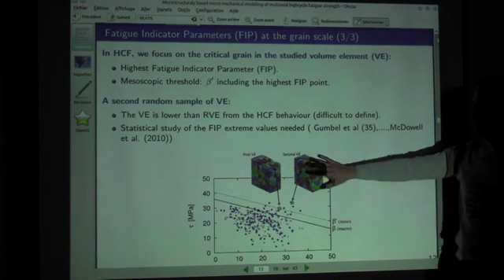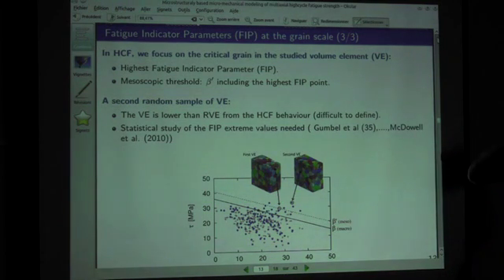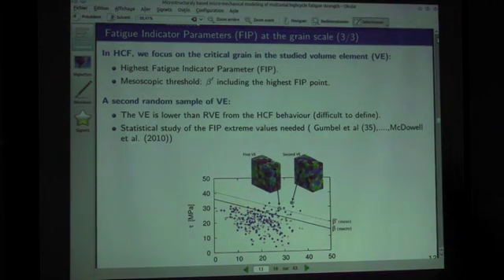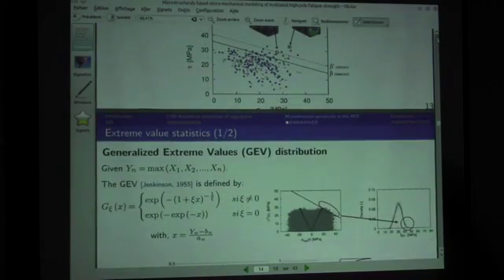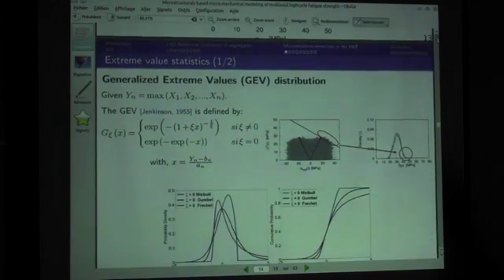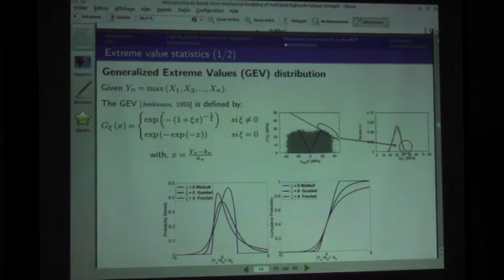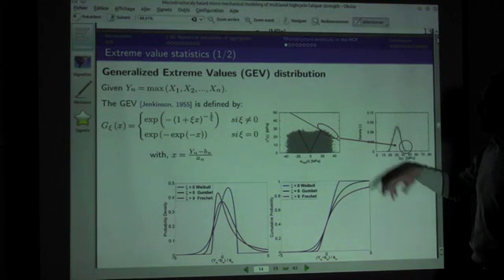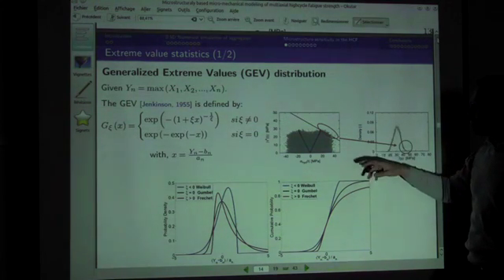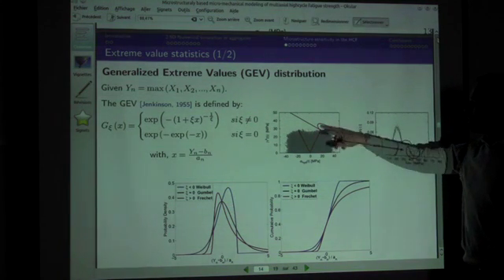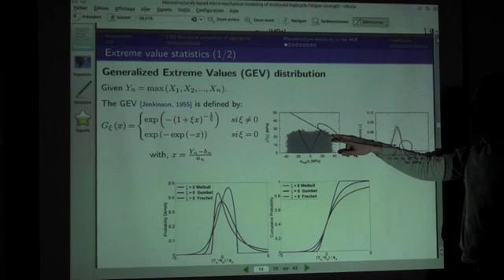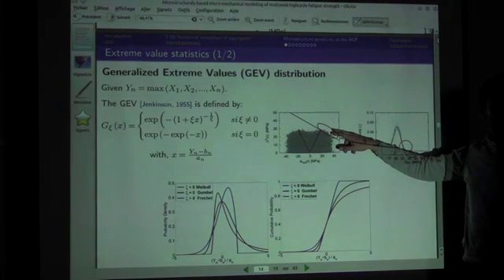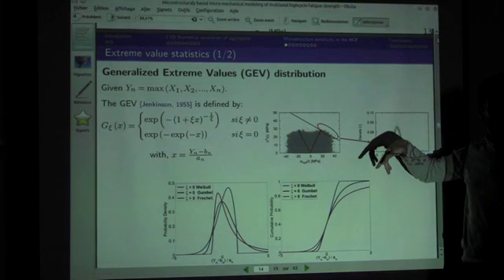You are representative on this aggregate from a constitutive modeling point of view. So the cyclic behavior is stabilized, but not the fatigue response. It's not sufficient doing just one computation. So what you have to do is many computations. And you have in particular to analyze not the one response, but all the responses of the aggregate or given microstructure to the loading. And you have in particular to analyze the effect of the extreme values of the response of the microstructure to the given loading.